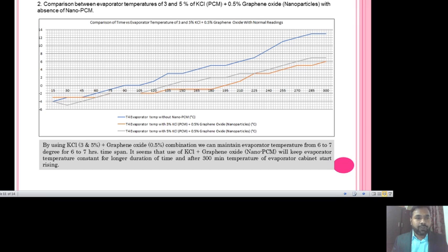The second graph relates to the KCl and graphene oxide combination. With 3% and 5% mass fraction of KCl along with 0.5% graphene oxide and water as a base fluid, we are maintaining the temperature around 6 to 7 degrees for 6 to 7 hours. So KCl plus graphene oxide nanoparticle keeps the evaporator temperature constant for a longer duration even though a power outage exists. Here also the blue line indicates that the temperature continuously increases in the absence of the Nano PCM. This is the main important thing, and these are the remarkable results we get with the nano phase change material.